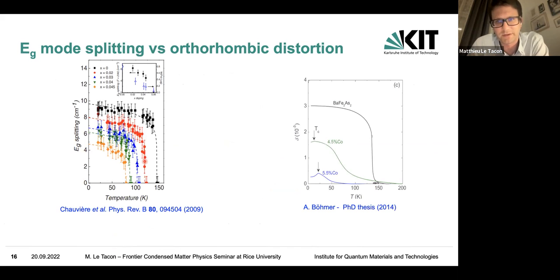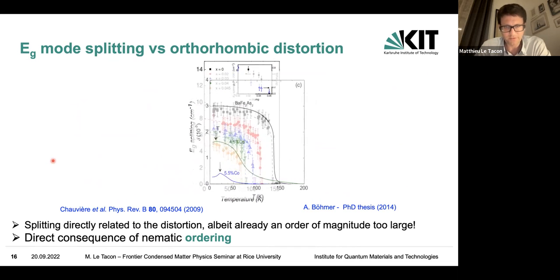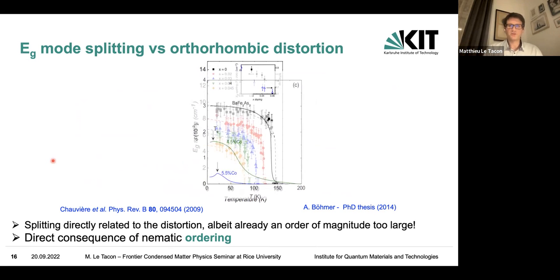So this is the thesis of a student from a few years back, and they've also measured in BaFe2As2 the structural distortion. So really the amplitude of the orthorhombic distortion. And I thought, well, we can compare that directly with the Eg splitting of the phonon. And if I put these two things together, I was really shocked. It works very well. So the Eg splitting is directly a measurement of the amplitude of the orthorhombic distortion, if you like.